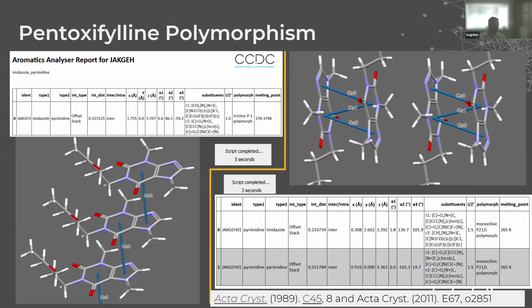The more stable compound on the left has only one aromatic interaction being expressed, but that interaction is propagated through essentially a line topology. Each molecule is interacting by one interaction with the molecule next to it. If you instead look at the polymorph on the right, we have two aromatic interactions, well, essentially 1.5 interactions happening between each molecule and its neighbor.